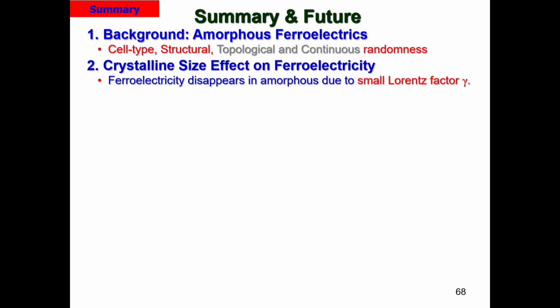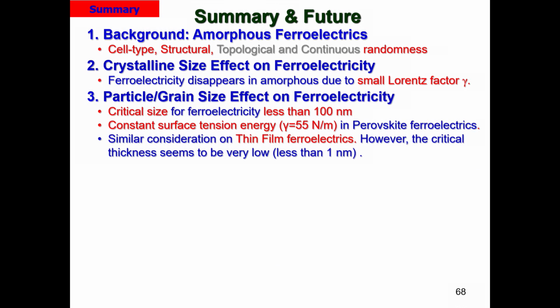Okay? So, summary and future. First, background: amorphous ferroelectrics. Unfortunately, in the cell type and structure, there are no amorphous ferroelectrics. So the crystalline size effect: ferroelectricity disappears in amorphous due to the small Lorentz factor, okay? And the critical particle size for ferroelectricity is less than 0.1 micrometer, or 100 nanometers, three-dimensionally. And the constant surface tension energy, you may say just a hydrostatic energy, okay? In the perovskite, this is almost constant, interestingly.